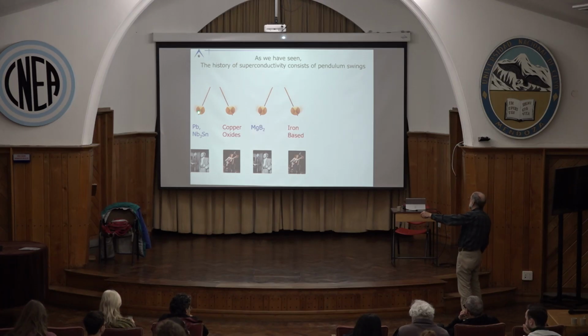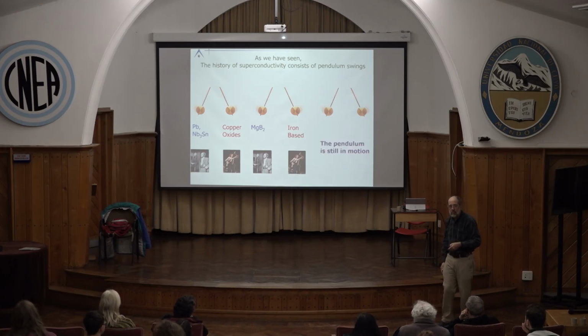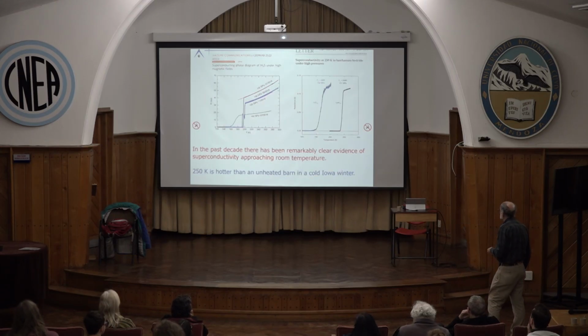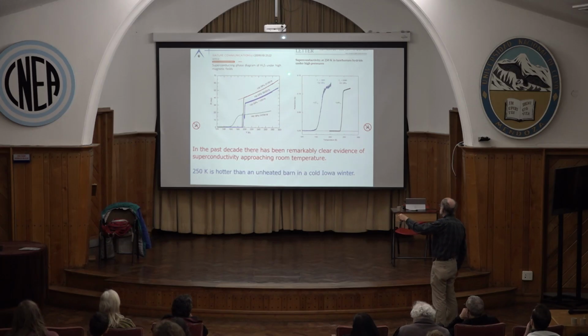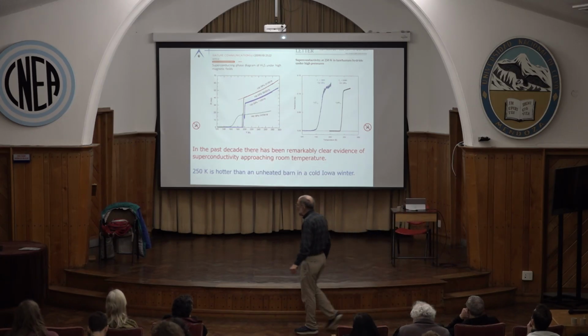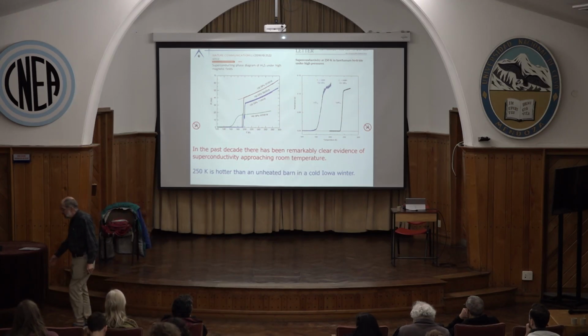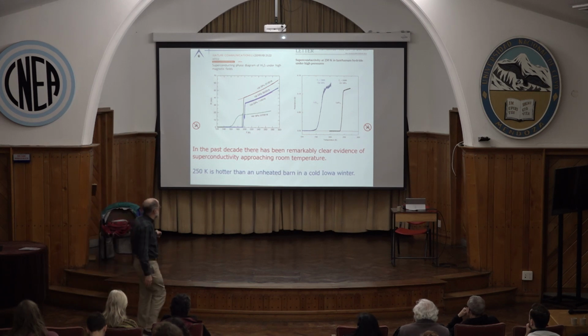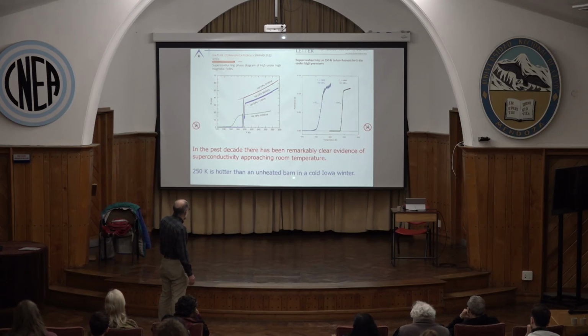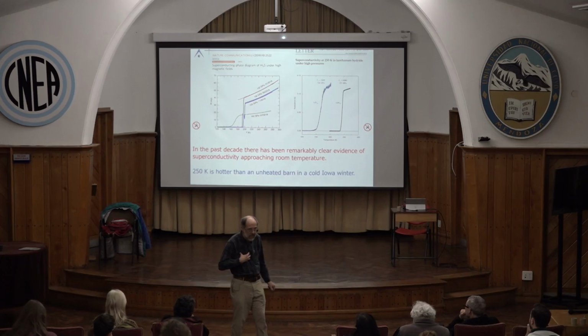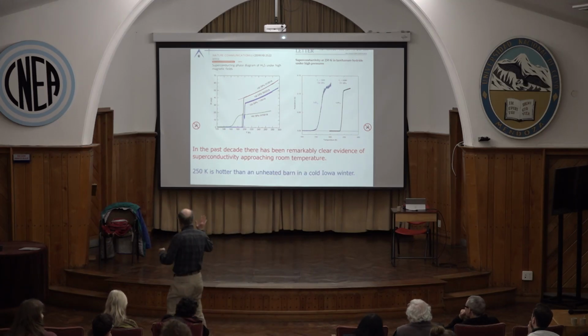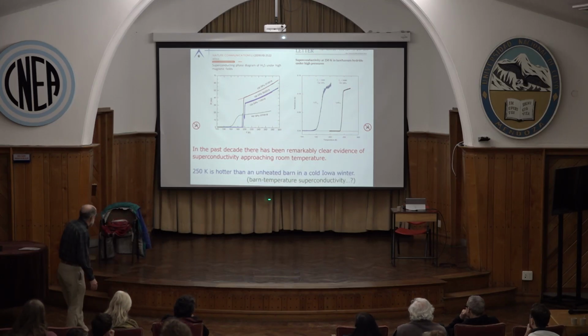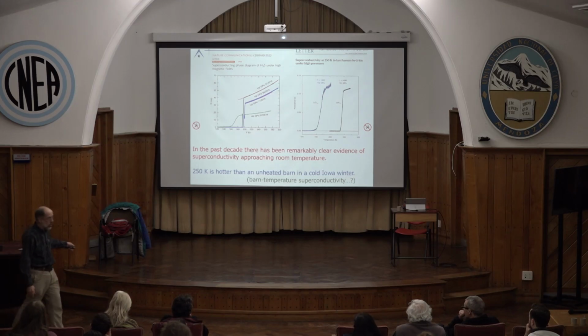So, where are we? Old school, new school, old school, new school. The pendulum is still in motion. Okay? Let's get to current days. There has been a phenomenal discovery in the last decade by Mikhail Eremets and colleagues. They found that if you can create under high pressures materials with lots of light elements, lots of stiff bonding, you can get TCs up to 200, up to 250. Okay? Now, 250 is hotter than an unheated barn in Iowa. It's almost hotter than the guest house room that I've been sleeping in because the heating broke. Okay? It's getting fixed. So, we don't have room temperature superconductivity, but we at least have barn temperature superconductivity.